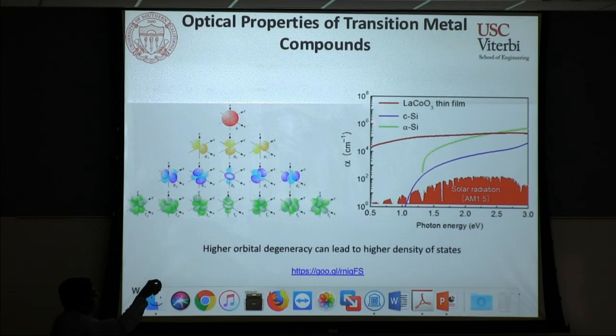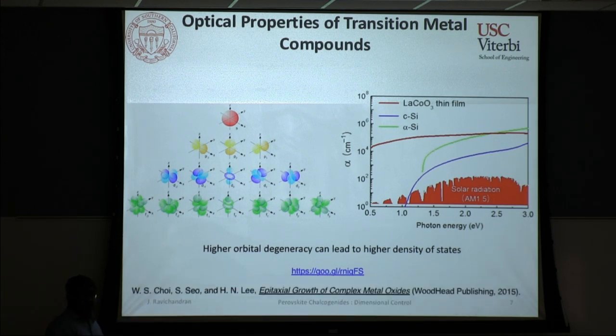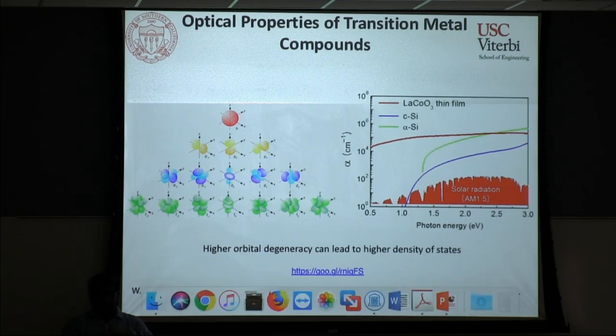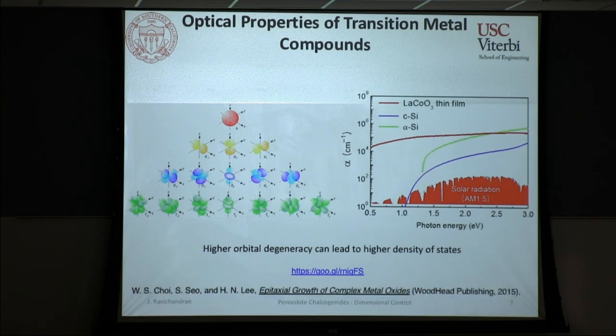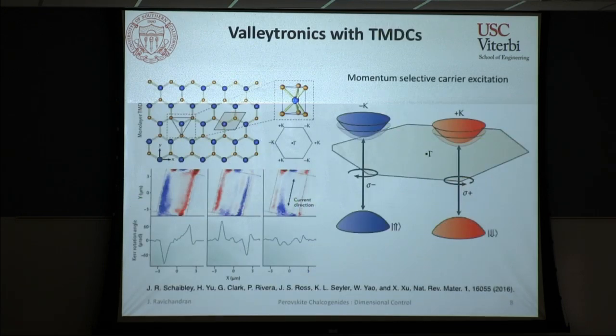But if you go to the lanthanum cobalt oxide, which has the d-band conduction, the absorption coefficient is a factor of 2 or even almost half an order of magnitude higher. That tells you that the d-band conduction can give rise to a large absorption coefficient. So this is interesting for solar cells, for example. If you can make a d-band system and still have some reasonable mobility, then you can think of ultrathin absorbers, and they can also give rise to good carrier separation mechanisms.